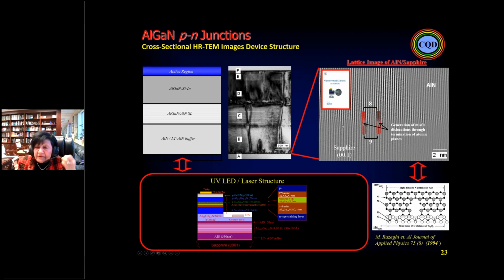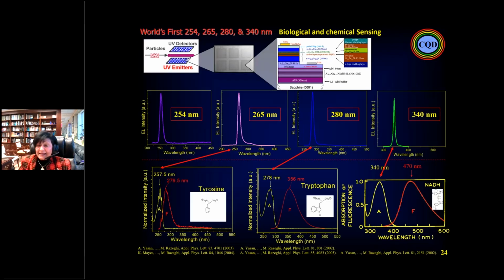And that is the perfection. And after that, as you can see, there is no defect on top of that. Of course, after that you are increasing the lattice mismatch again, because it's very sophisticated what we have to do. But the beauty of this material is, as it's a large band gap, very strong covalent, the mobility of the defect is very low. So we can make, again, the LED and we can make the laser.